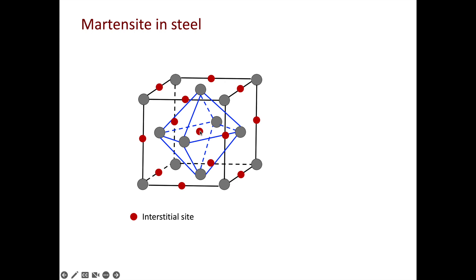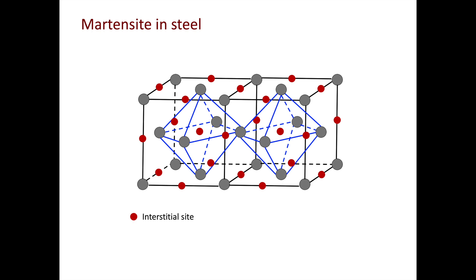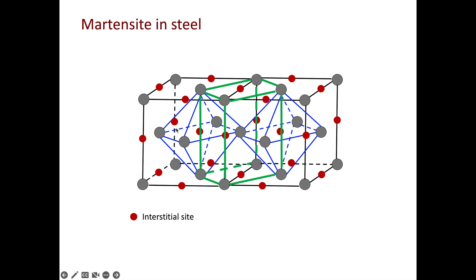We can extend the unit cell — just from a very simple rearrangement, you can form a new crystal structure highlighted by the green box. And this is the martensite. Looking more closely at this martensite unit cell: first, it has a BCT (body-centered tetragonal) crystal structure. Second, a lot of carbon atoms now sit on the vertical edges of this BCT structure.